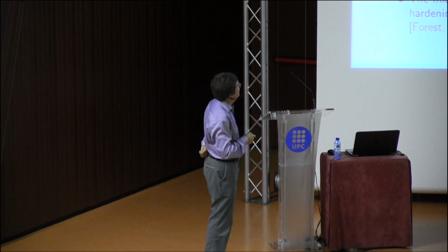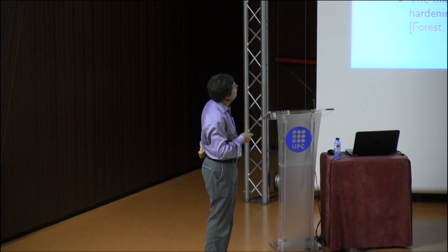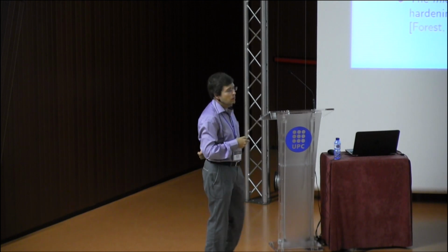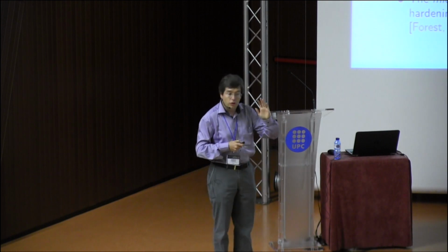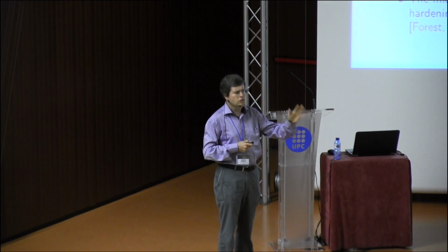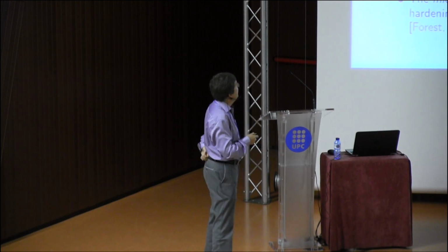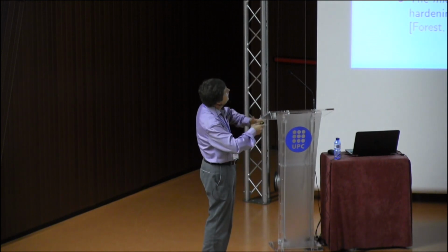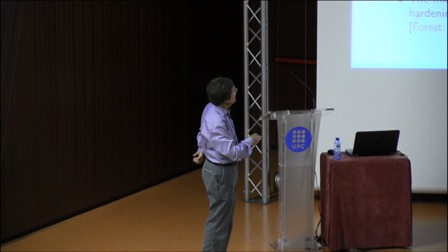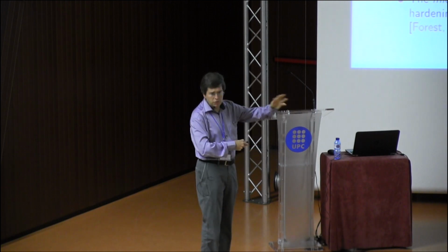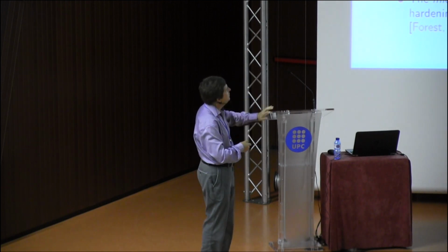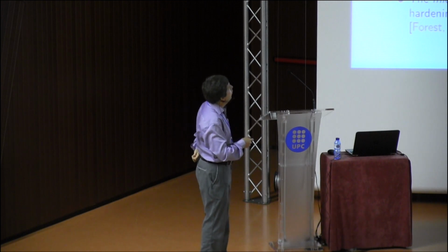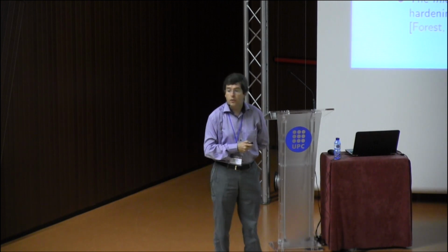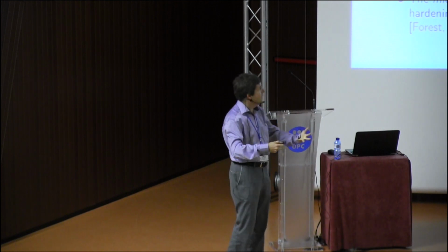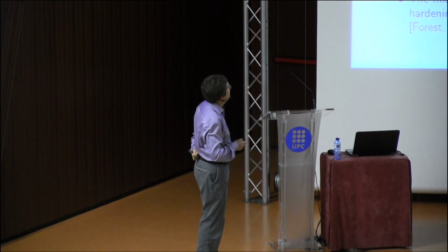In his idea, it was related to the fact that in the microstructure you can have some specific physical directions which are not necessarily material directions, so they don't follow the deformation gradient, but they are stretched and rotated by a micro-deformation tensor. It means a full general second-order tensor without any symmetry, with the property that this field is not necessarily compatible because it is not related to the material deformation.